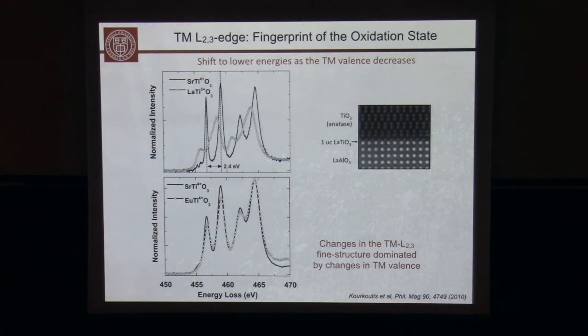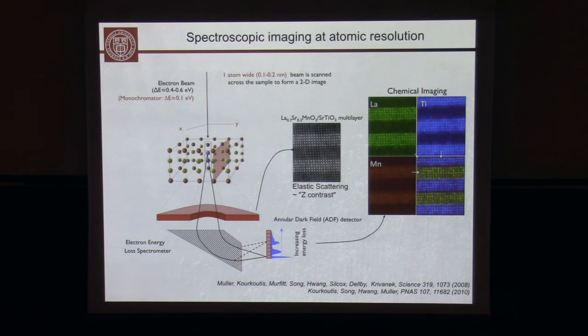Now, what has happened in the last decade or 15 years or so, the community has produced first commercial aberration correctors, which correct aberrations of the electron lens. And that means we can not only measure in line mode, but we can now imagine scanning, instead of just taking an elastic image, simultaneously recording a full spectrum at each point in the image. So imagine you scan your beam across, and at each point you collect the elastic signal and the inelastic signal with very high efficiency. And that allows us to extract chemical maps.